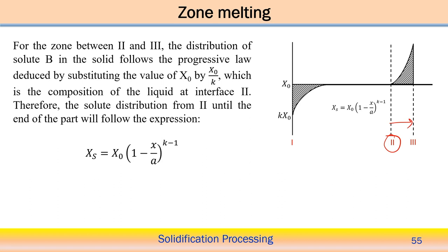So, from here to here we can follow the expression that xs equal to x0 into (1 minus x by a) to the power k minus 1. So here we can say this kind of expression is valid for the solute distribution from point 2 until the end part. From here to here, at this distance, this expression is valid.